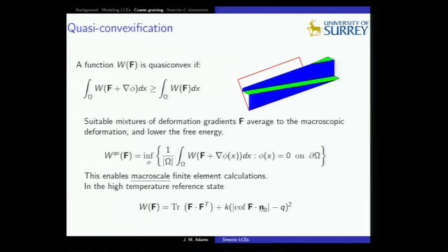So you get something that looks just like a neo-Hookean term, and then this second term that tells you about layer spacing. So this is simpler than the nematic phase, and what's happened is there's some of the terms from the spontaneous deformation that have gone into this term in the energy, which is why you get a different value of Q here. So essentially you have to complete the square.